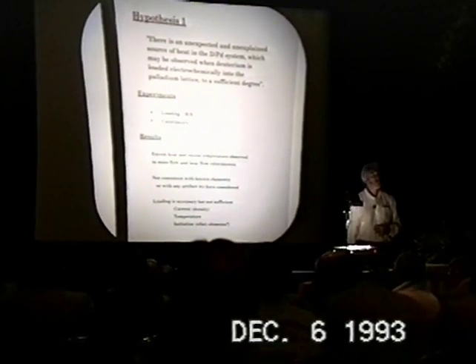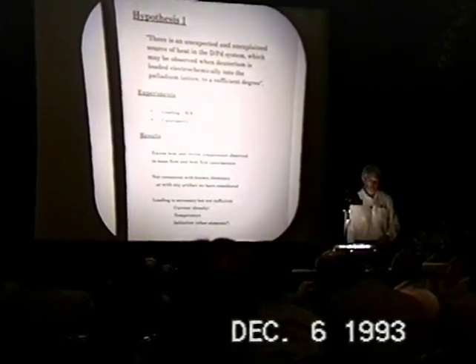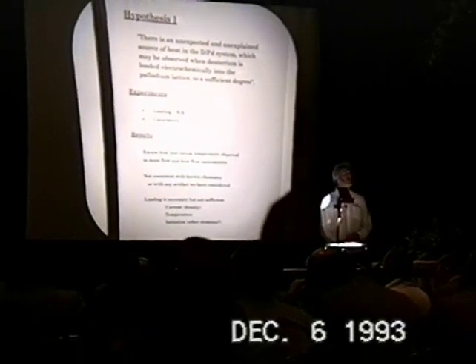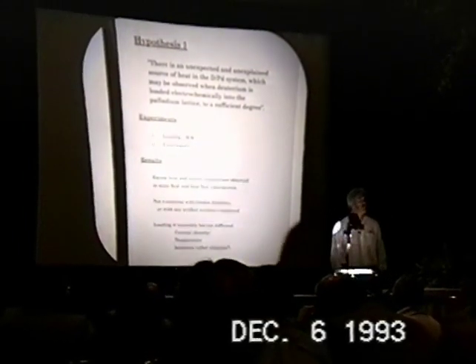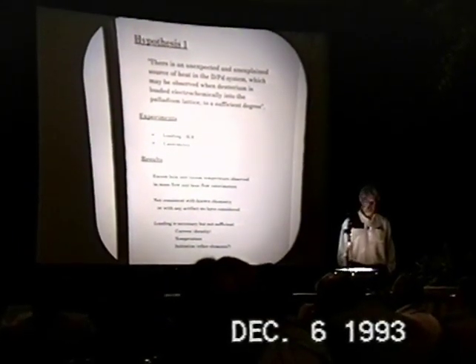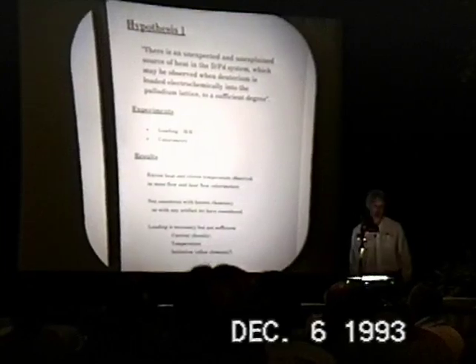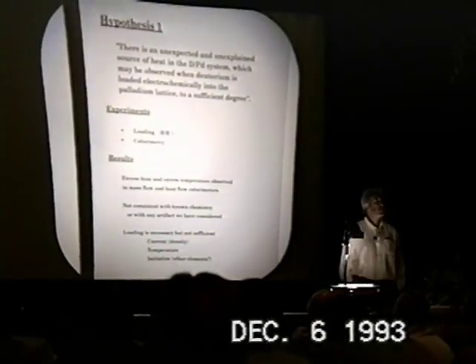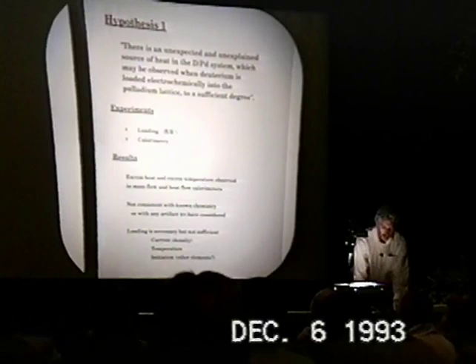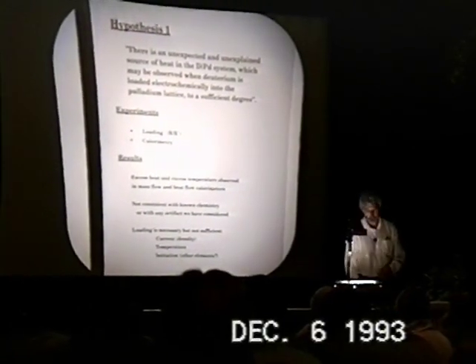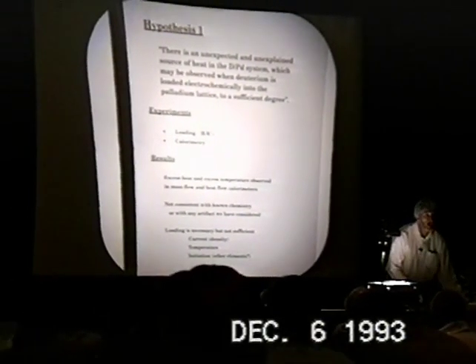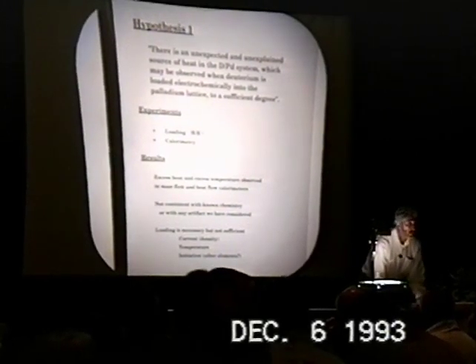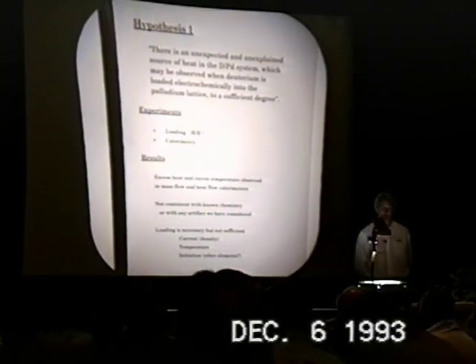One of my colleagues, Steve Crouch-Baker, likes to say, an experiment is done for one reason and one reason only, to test a hypothesis. It looks back and investigates the hypothesis upon which we embarked on this strange research program. That hypothesis was that there was an unexpected and unexplained source of heat buried somewhere in the deuterium-palladium system, and that this source of heat was observable under the condition of high loading.